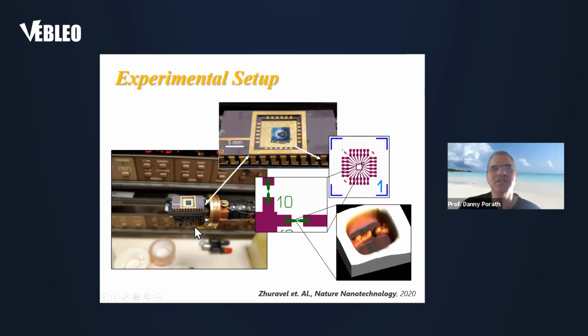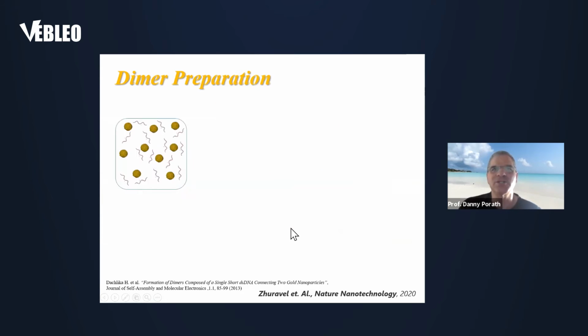And here you can see the experimental system. Here you can see the chip with a lot of electrodes shown here. And somewhere in between the electrodes, we have these two nano electrodes with 30 nanometers in between. They can be seen here in the AFM image, and there we can perform the measurements.